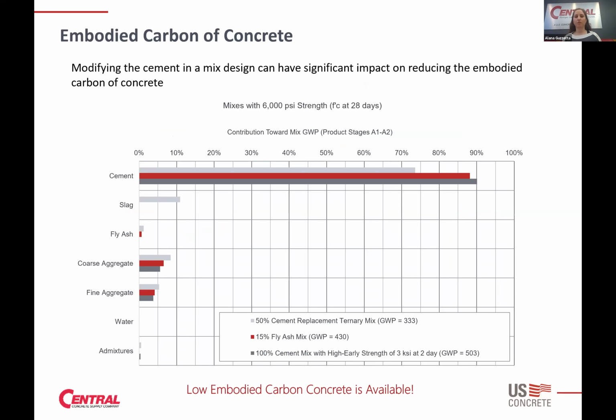Looking at the mix overall, this is a breakdown of the GWP for 3 different mixes, and looking at where the majority of that embodied carbon is coming from. As Michael said in his presentation, it could be about 70% comes from cement. And so in this specific breakdown, we took a look at 3 different mixes. The dark gray bars are a 100% cement mix. So that means the only powder in the mix is Portland cement.